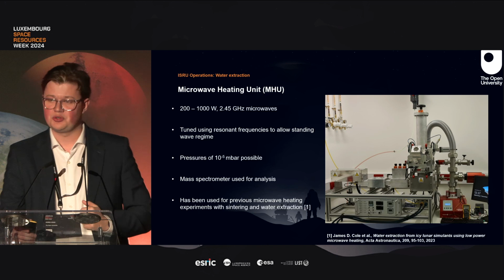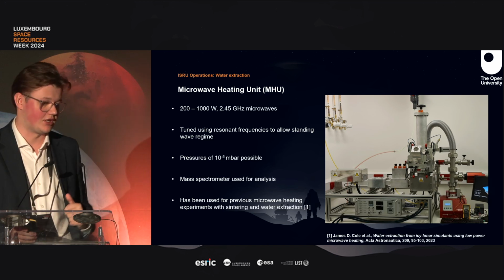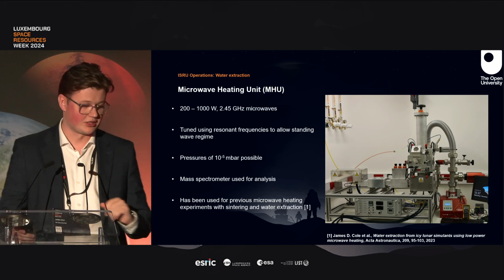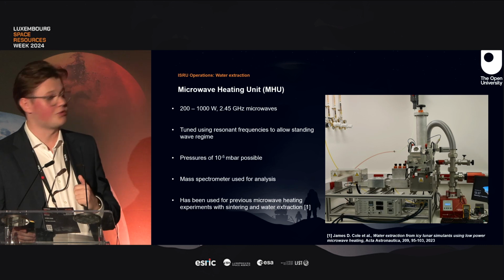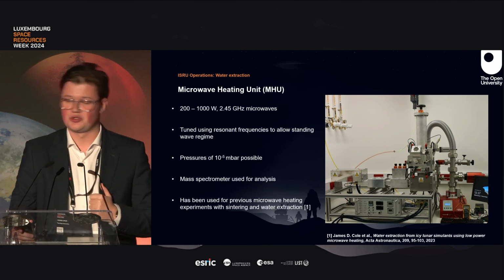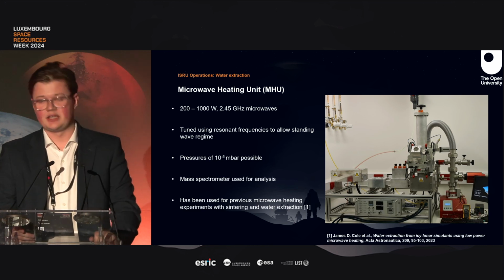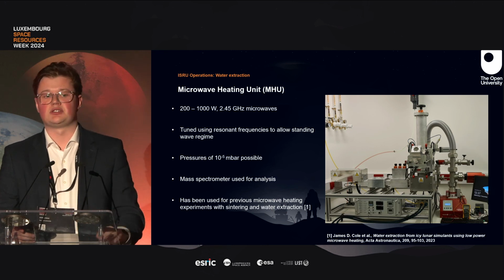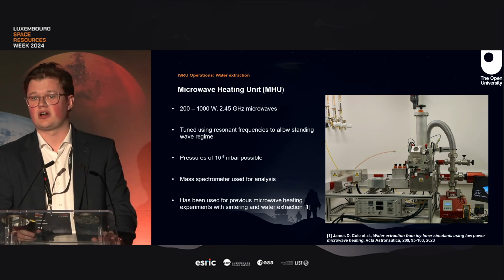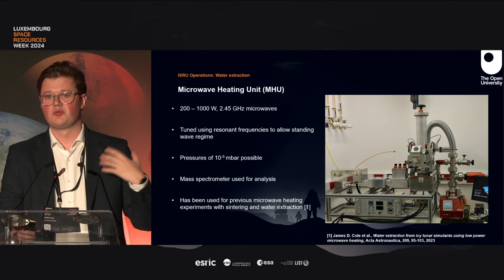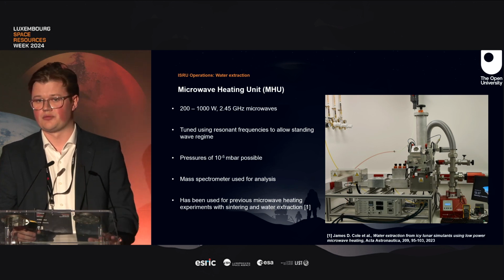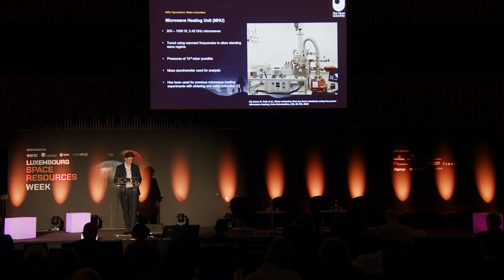So at the Open University, we have a microwave heating unit. I'm sure some of you have seen this picture countless times. It can produce microwaves between 200 and 1,000 watts at 2.45 gigahertz. And it uses a standing wave regime to lead to areas with very high electric fields, which allow you to place the samples in those spots and get hot spots and then thermal runaway.